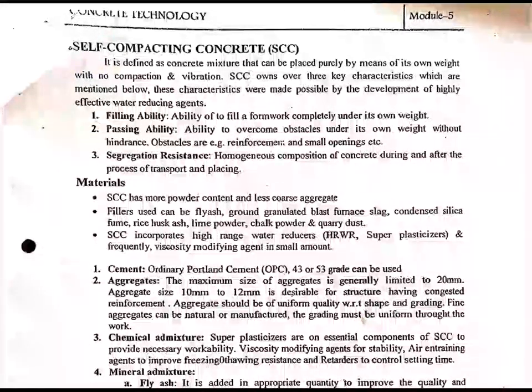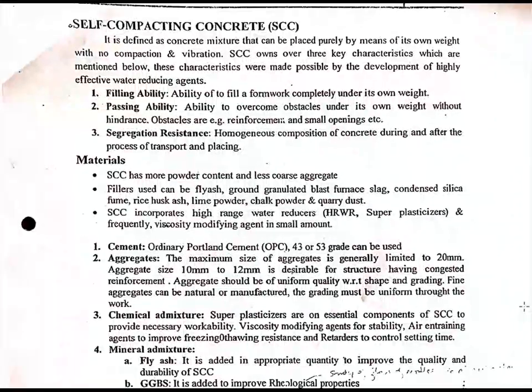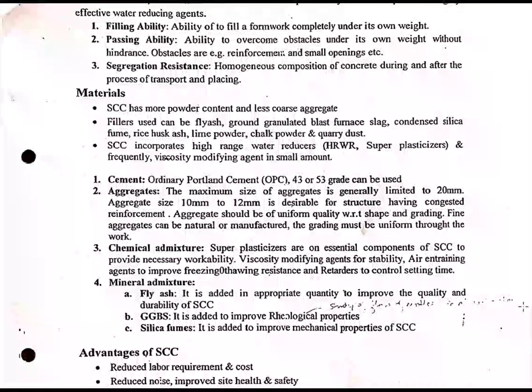So let us move on to the materials required in the concrete. As usual, the normal concrete contains cement, fine aggregate, coarse aggregate, admixtures, chemical or mineral, etc. So here in self-compacting concrete, we use ordinary Portland cement, that is normal cement. Aggregate used should be less than 20 mm. Usually, to maintain the flowability of the concrete, we have to use aggregates of size 10 mm to 12 mm. Note this point: 10 mm to 12 mm aggregates we have to use in self-compacting concrete.